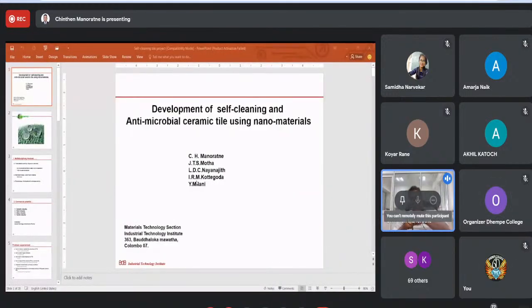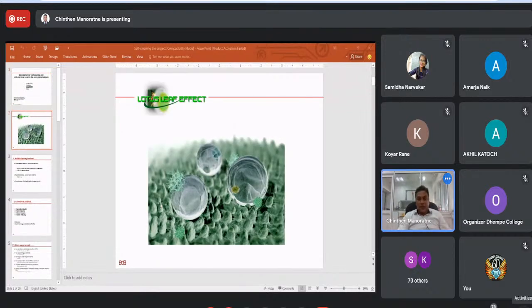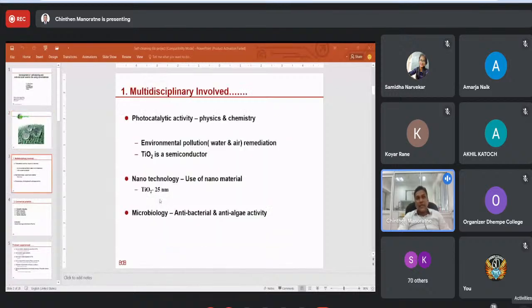Now this is another study we have done some time ago. One of the ceramic companies collaborated with us to develop a self-cleaning tile based on nanomaterials. More studies are going on in this area, developing self-cleaning materials with antimicrobial property. I won't explain these because they are freely available. In the ceramic industry, high temperature is employed. Normally they fire at 1000 or maybe 1200, and this nanomaterial, especially titanium dioxide, does not withstand that much temperature. At some mild temperature, about 500, it converts to rutile, a less photocatalytic material.